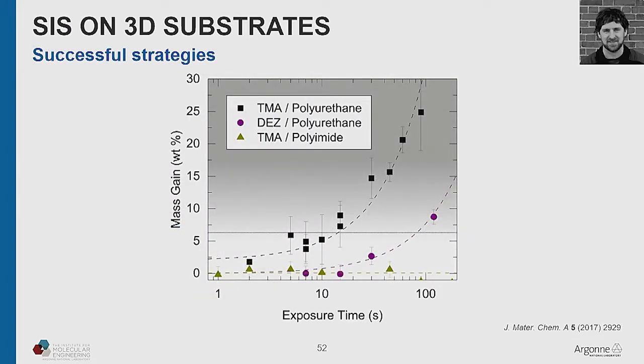For reasons that I don't really have time to explain, we use mass gain of the foam as a proxy for what you don't want to have happening, that going up in smoke. And we define kind of an arbitrary line of mass gain, which we want to stay under to avoid degradation of the material. And so the normal TMA with polyurethane, if you stay at a low enough exposure time, you can stay below that line. If you go to the zinc, you have a bigger processing window, and if you go to a foam like polyimide, you actually have a very large processing window. So any of those strategies work.